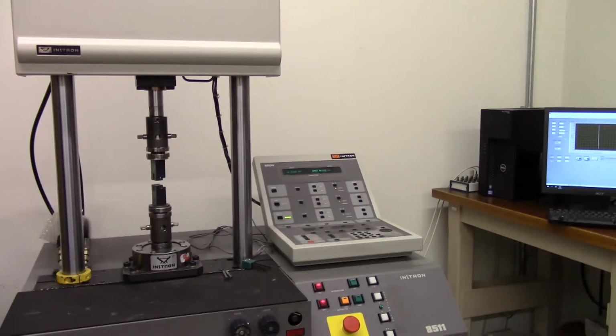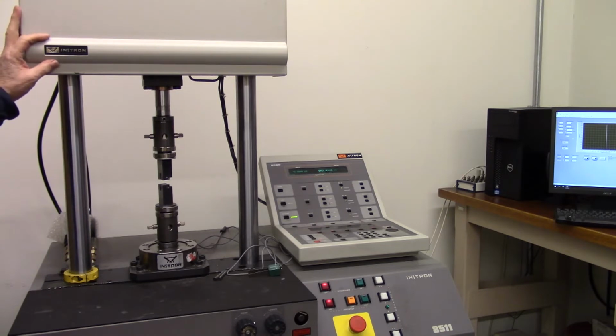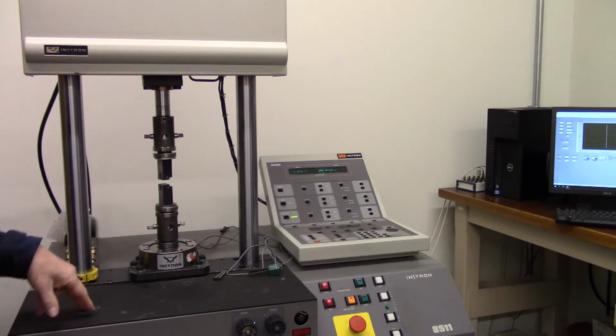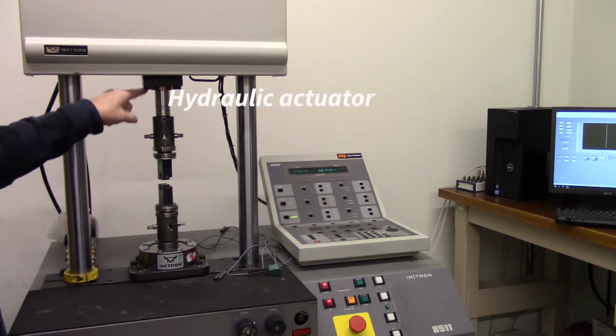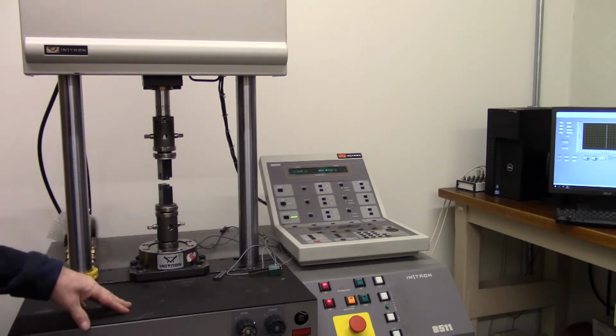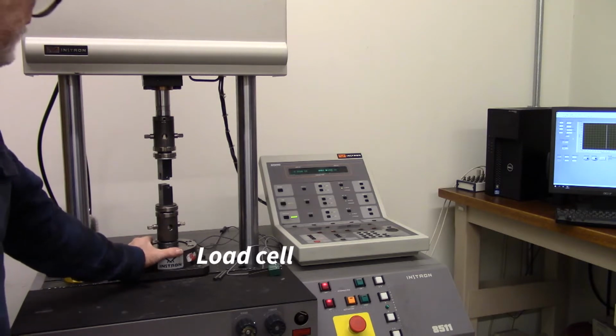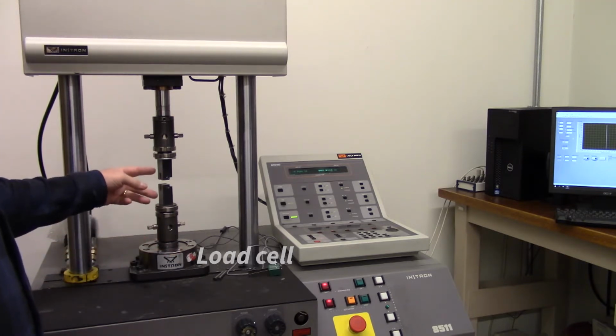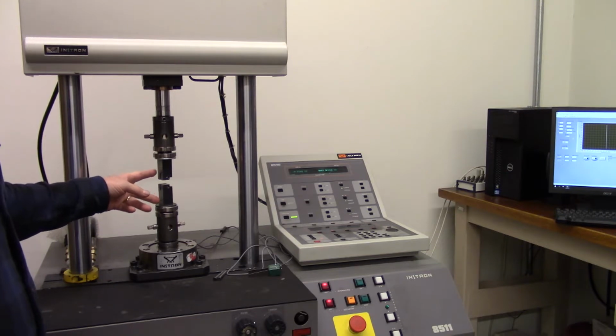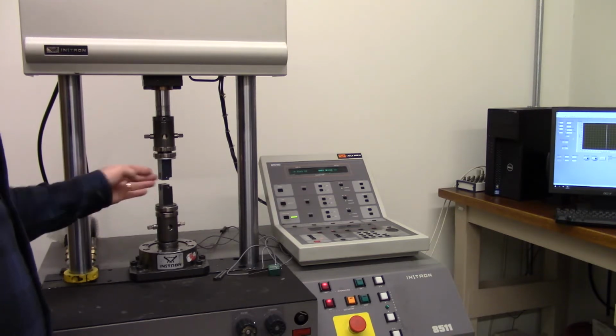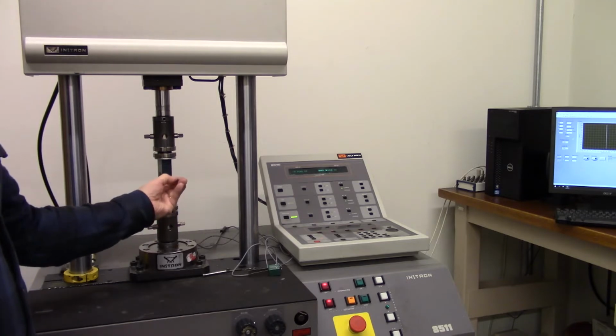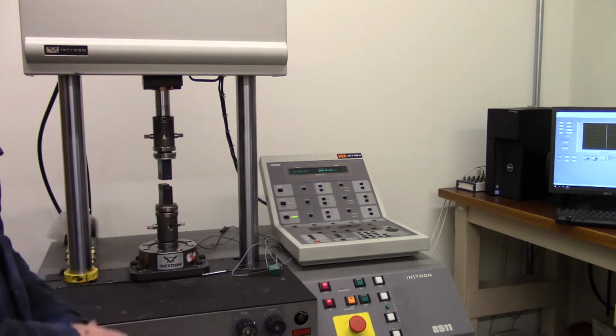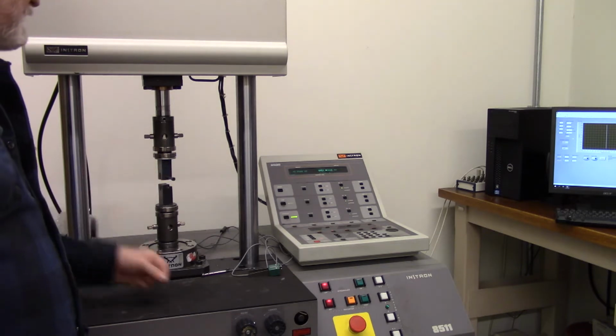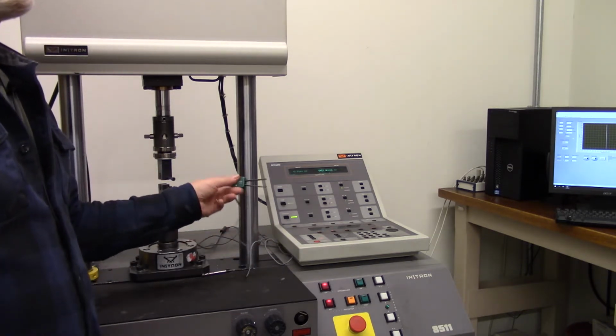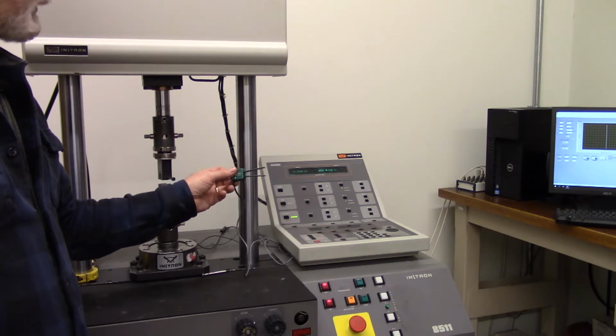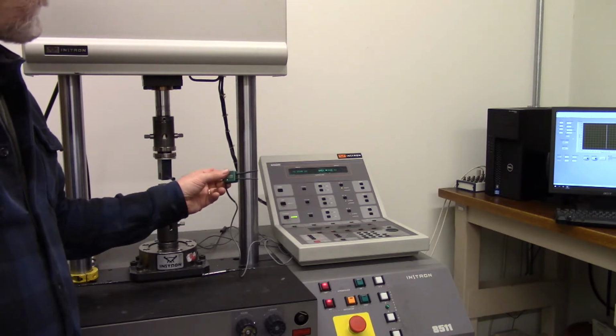Let's take a look at this load frame here. This is the Instron 8511. It's a servo hydraulic machine, which means there's a hydraulic pump that drives this actuator up and down with a range of plus or minus 50 millimeters. We have our load cell down below here. And then we have our adapters here and our compact tension fixtures. So our specimens will slide in, we'll pass a pin through to grab the specimens, and that'll allow us to apply our load during the test. We have a clip gauge here that's going to allow us to monitor and record the opening of the crack.